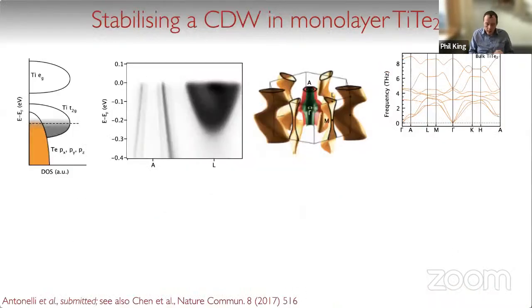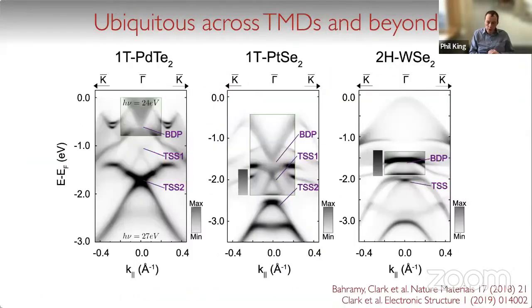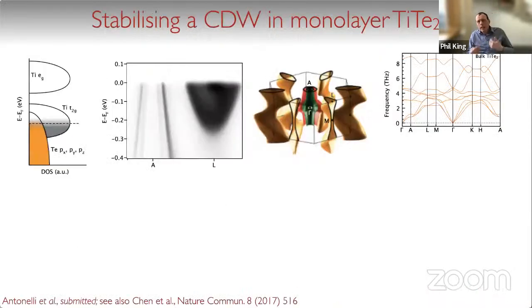But also in some of the other structural polymorphs, for example, the 2H system, you can see, again, a bulk Dirac cone and now a rather confined topological surface state derived from the same mechanism. So this is something that we think is very general across the transition metal dichalcogenides. And I'd like to talk for a few minutes now about how this is actually important to a rather separate topic, the charge density wave